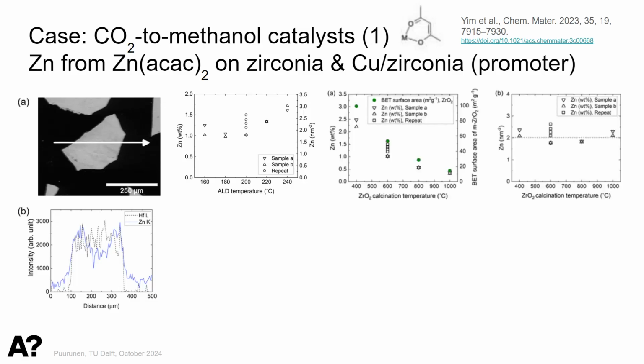And what is typical for ALD is that, once you are varying the surface area, we have been calcining our zirconia at different temperatures. Here the green spots show you the specific surface area. It's coming down strongly. So is the zinc content. But if you then calculate how many zinc atoms you have per square nanometer, that's always about 2 per square nanometer after one reaction. That's irrespective of the specific surface area or the calcination temperature of the support.